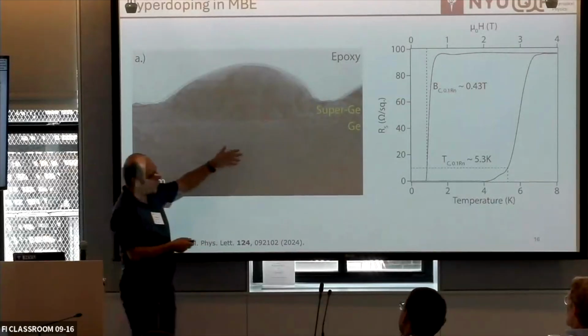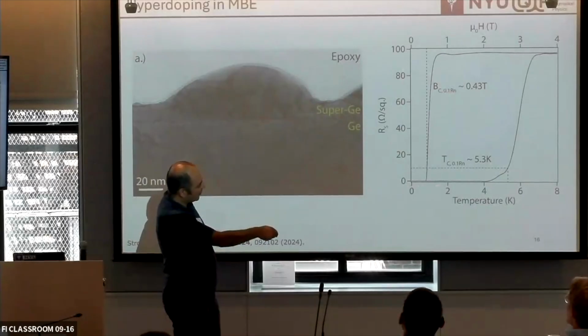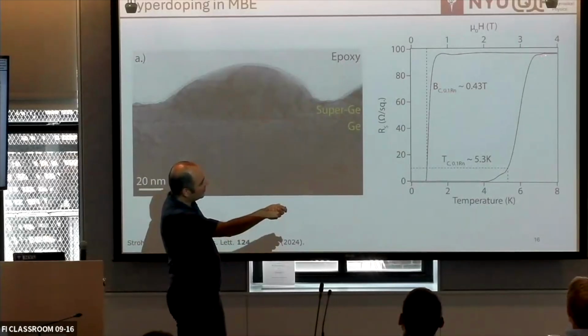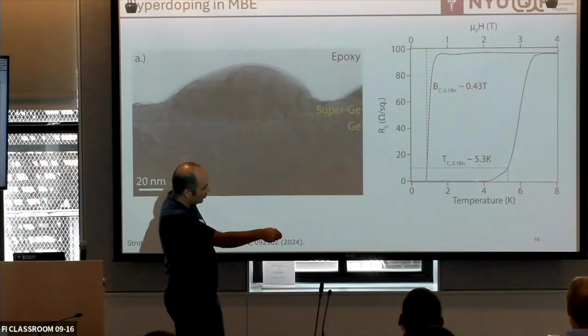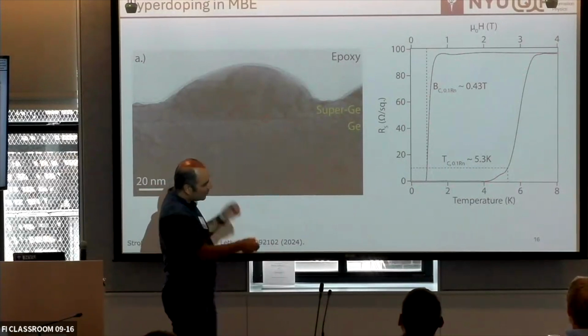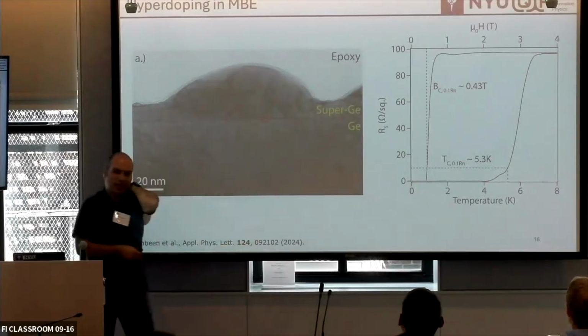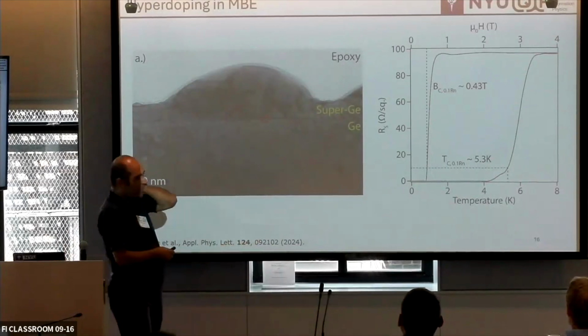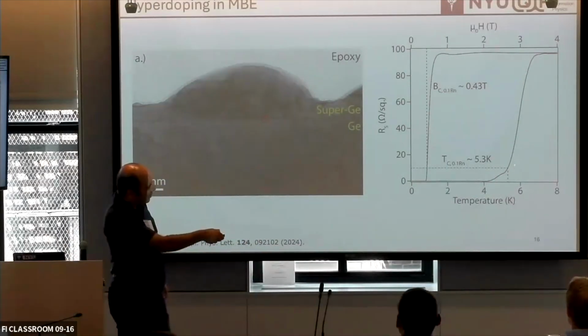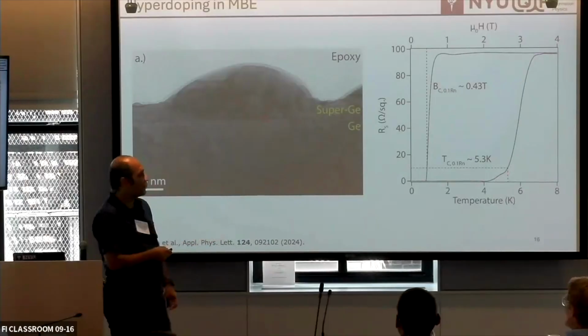So you can make it superconducting for sure. This is R versus temperature. And you see that basically the curve, the black one, shows us something that goes to 0 around 4 Kelvin, and then there is a BC. They are very reminiscent of disordered superconductivity in so many ways. Usually there is a band, and then there's another band, and then it kind of goes to a superconductor.